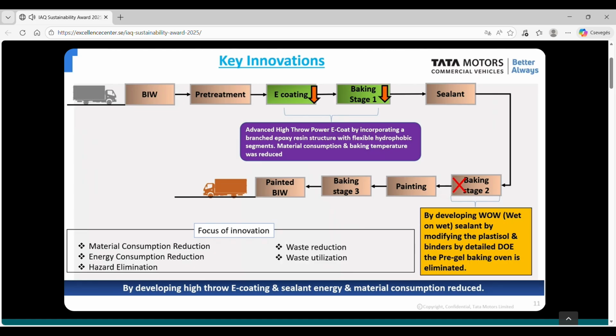We developed an advanced high-throw power E-coat. This was achieved by incorporating a branched epoxy resin structure with flexible hydrophobic segments, and this reduced both material consumption and baking temperature, leading to lower energy use. The second is the WOW sealant, which is wet on wet sealant. This breakthrough allows us to eliminate baking stage 2 entirely, which was previously a major energy consumer. By removing this oven, we achieved a substantial energy saving and reduced operational complexity.